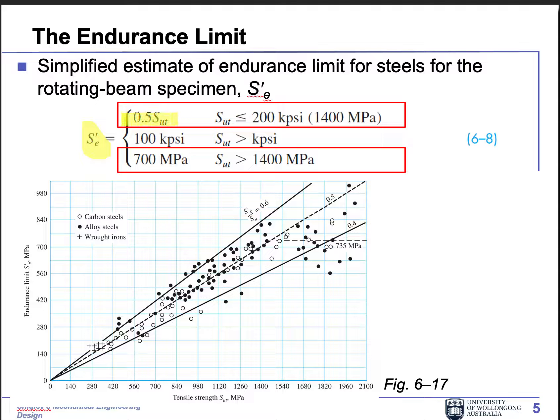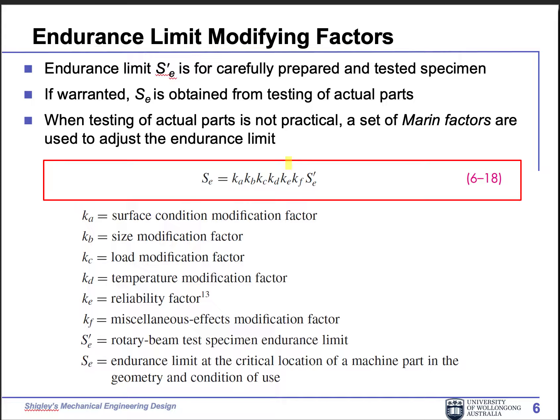Se prime is normally half of the ultimate tensile strength. For very strong materials, it saturates at 700 MPa. You get Se prime from equation 6.8. However, the actual component is not carefully prepared — you have different preparation methods, fabrication methods, and different geometry compared to the standard sample. So we have to add adjusting factors. The most important ones are Ka, Kb, and Kc — these three you always have to consider. With Ka, Kb, Kc, and Se prime, you get the actual endurance limit Se.